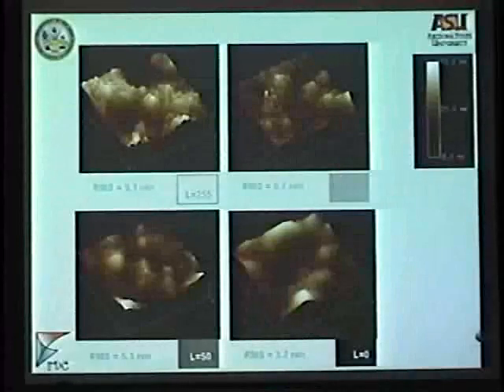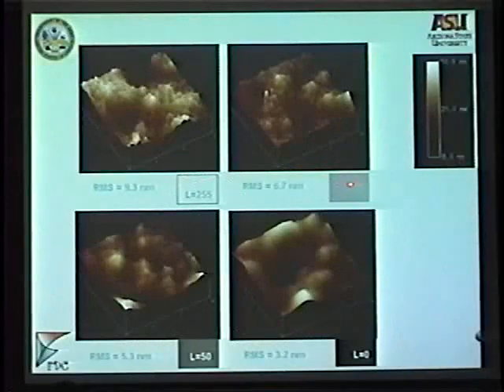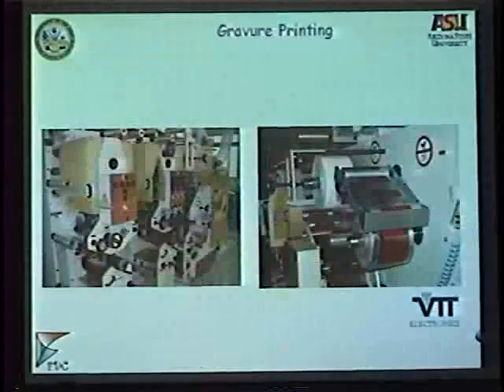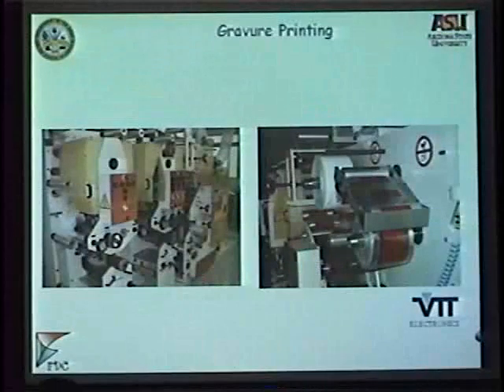Now the surface roughness of these films, as you treat them with the oxidizer, the more oxidizer you put, going from high brightness basically, so white as received, all the way up to complete darkness. Here you could see that the RMS is decreasing. So there is some sort of washing out of the PEDOT from the substrate to smooth the substrate out. Now the question was to Professor Lee before about the